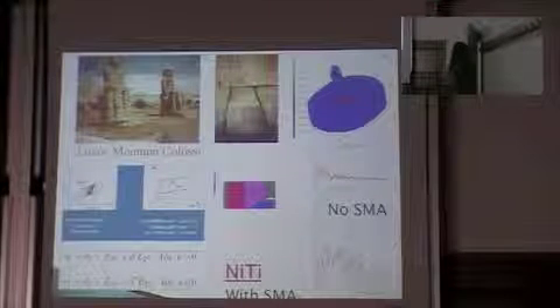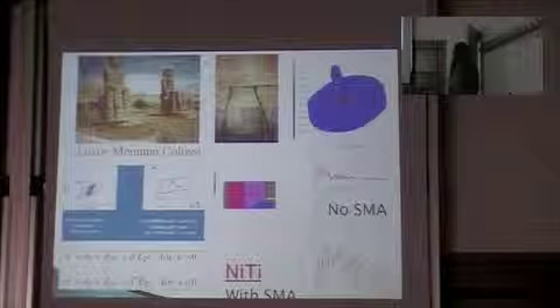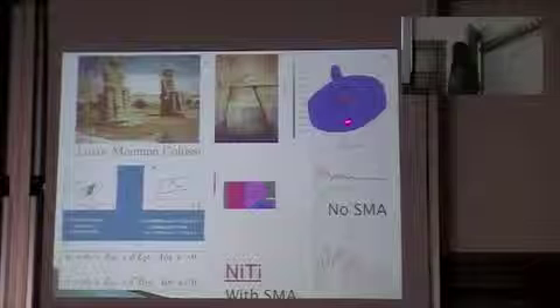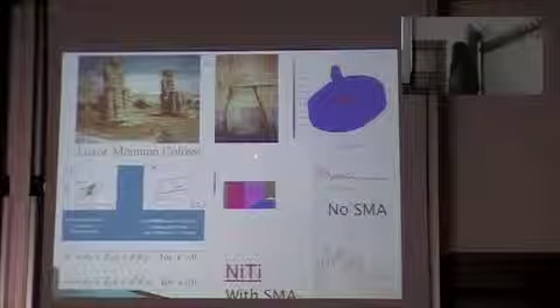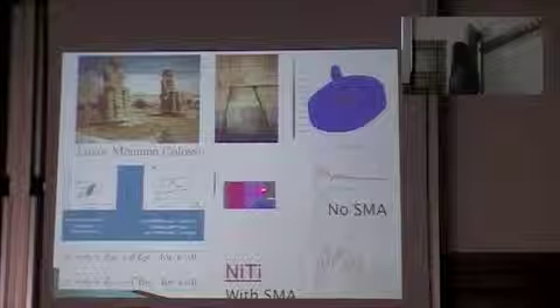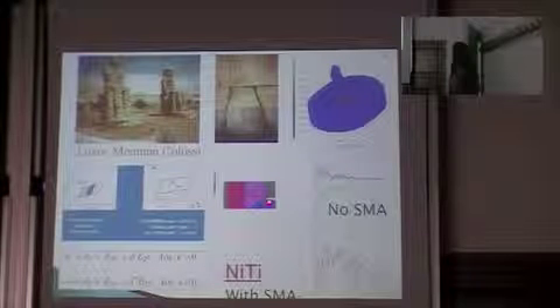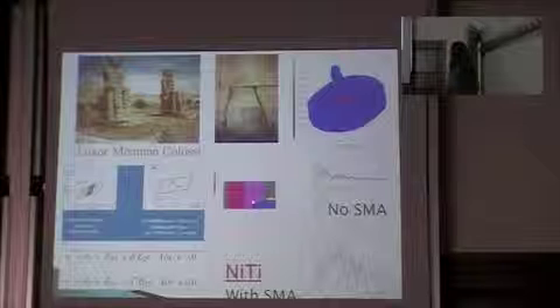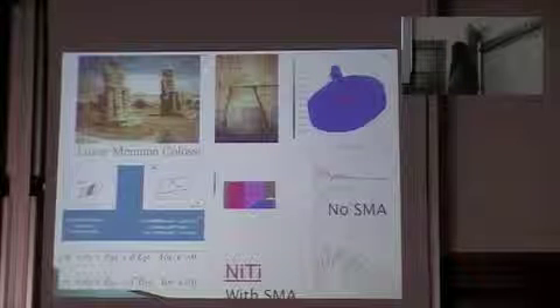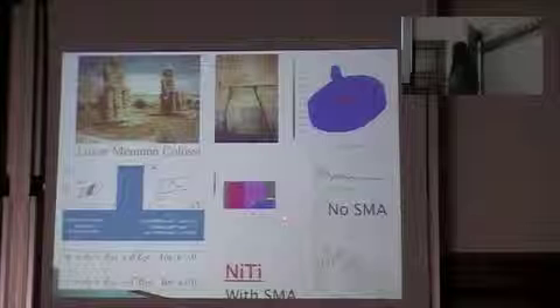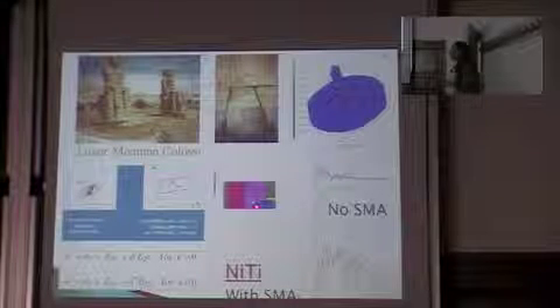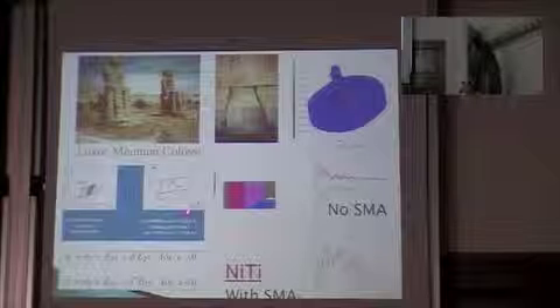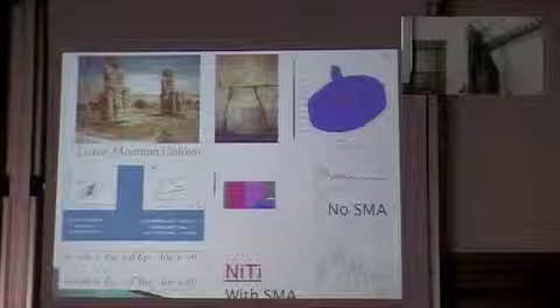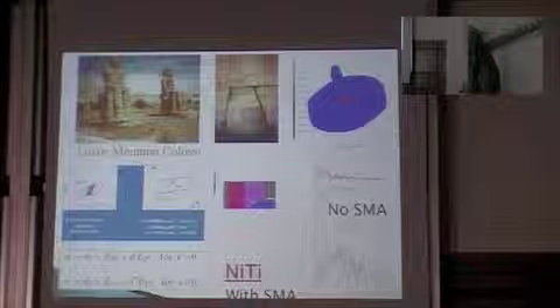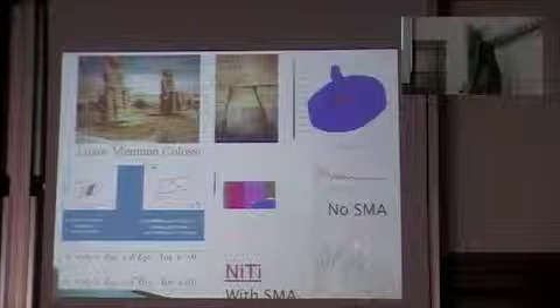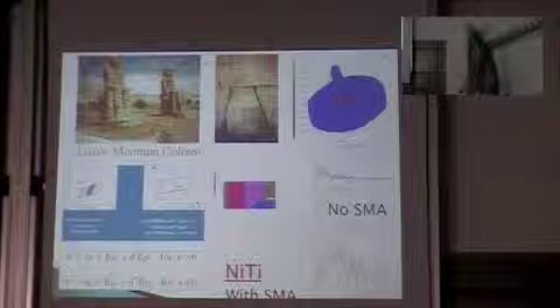The model was schematized by finite element, where the cracks were included by modeling a contact problem. And here is shown the relative displacement of two nodes at opposite edges of the cracks, with and without a link of a wire that had the constitutive law of a bilinear nickel-titanium shape memory alloy. And we see how the relative displacement with the addition of this device is limited compared to the case without it.